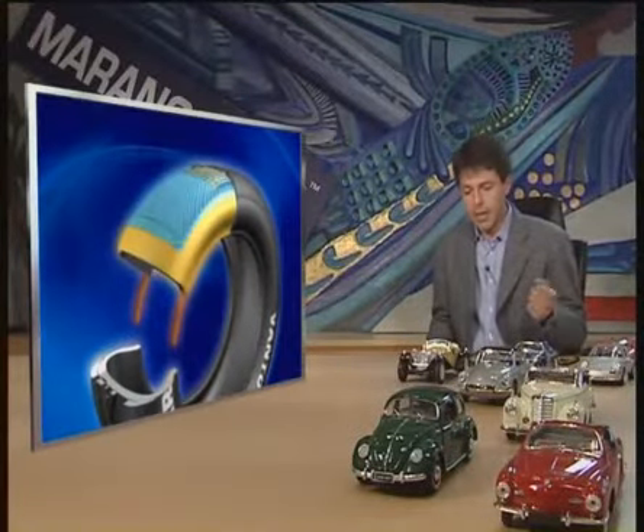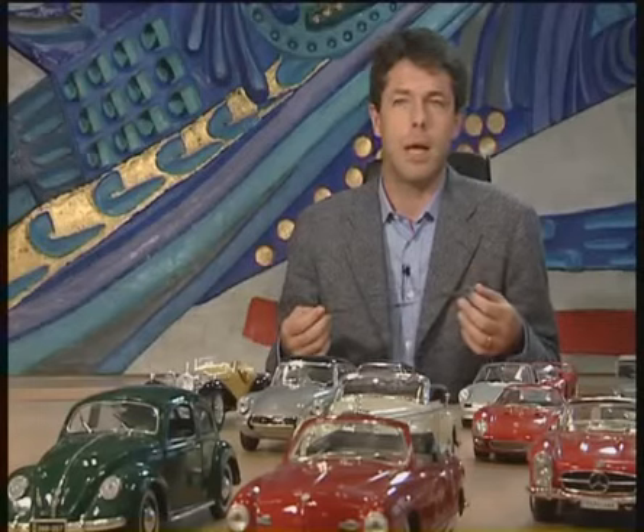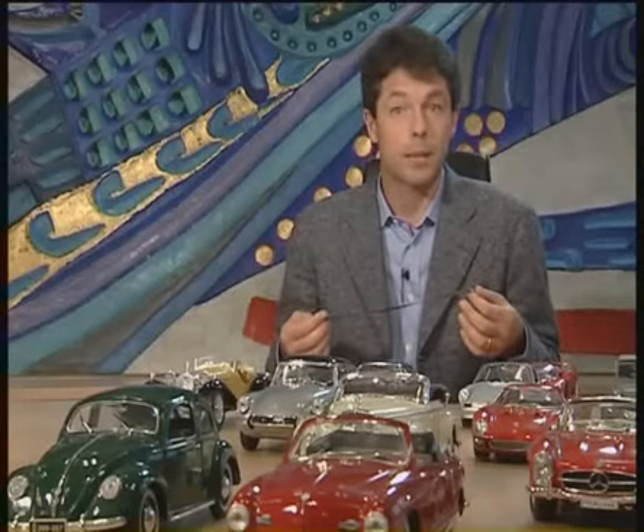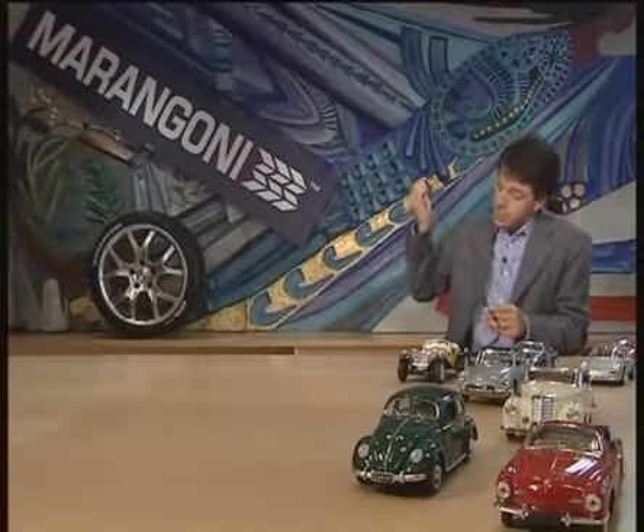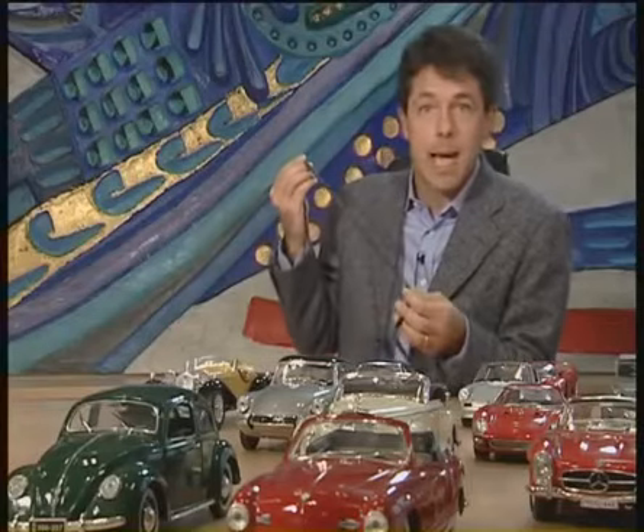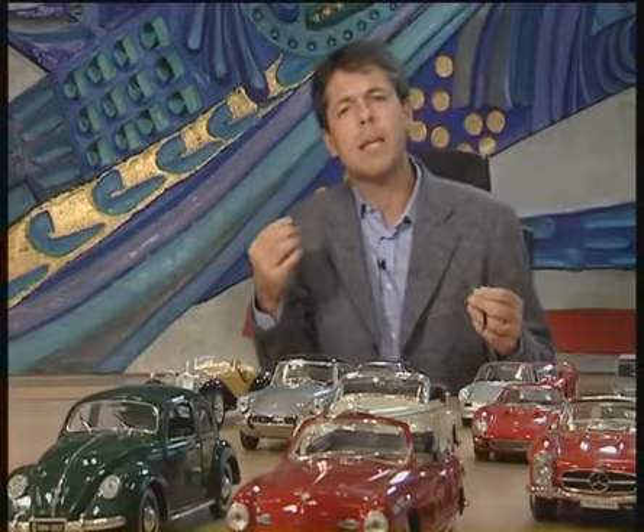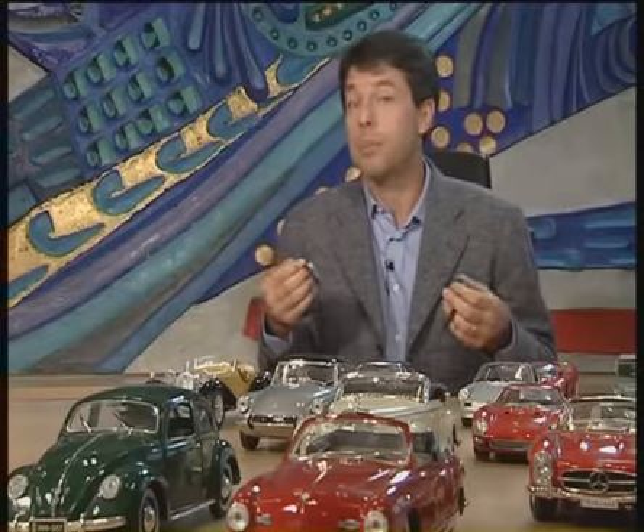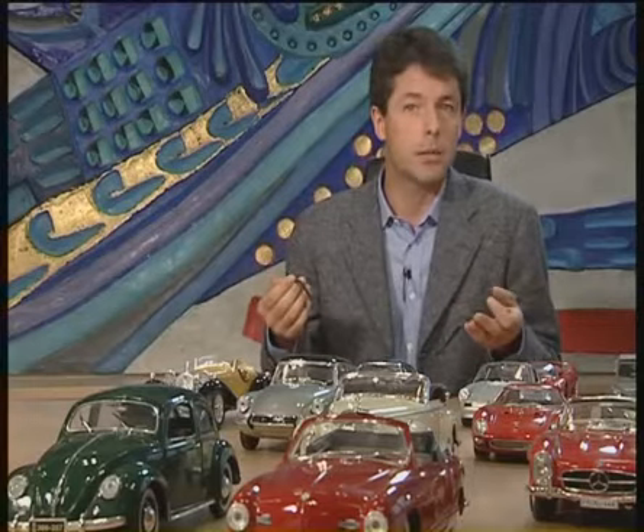As you will recall, a rubberized nylon belt is mounted and wrapped over the two metal belts. This is no more than 8 millimeters wide and has one or two layers, depending on the size and type of the tire. The nylon fibers are arranged in the direction of the tire rolling plane. The use of the nylon spiral belt represents advanced technology and is usually reserved for the UHP, or Ultra High Performance, and HP, High Performance, lines. Marangoni has extended the use of this technique to its entire product line.